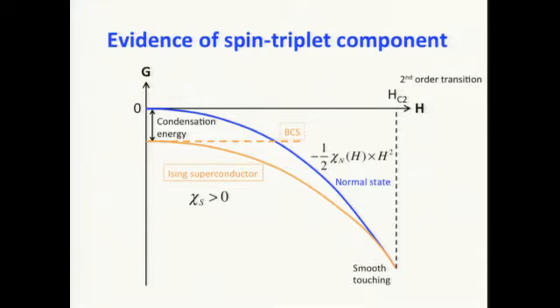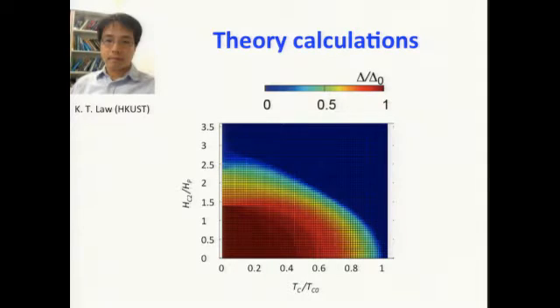This qualitative theoretical picture was put down by our theory collaborator KT Law from HKUST. What he calculated, using a realistic band structure of niobium diselenide, is the whole phase diagram. You can see that the order parameter varies smoothly with increasing magnetic field. It's all a second order transition.